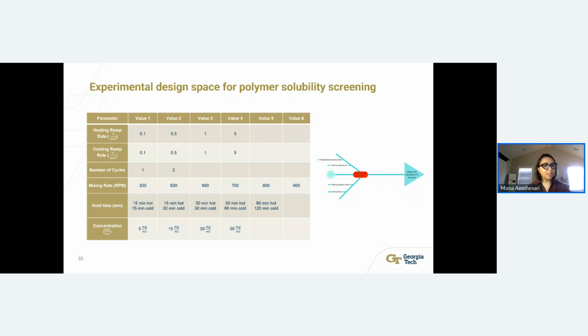The number of cycles is another parameter that we look at. We just keep it at 1 cycle or 2 cycles for faster data collection. We looked at a wide range of mixing rates, from I think 200 to 900 RPM, and different hold time combinations, from 15 minutes for hot and cold, which is very normal with pharma studies, to a maximum of 60 minutes at hot temperature and 2 hours at cold temperature. We also looked at different concentrations of the material.